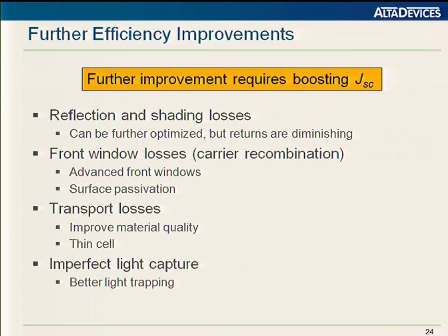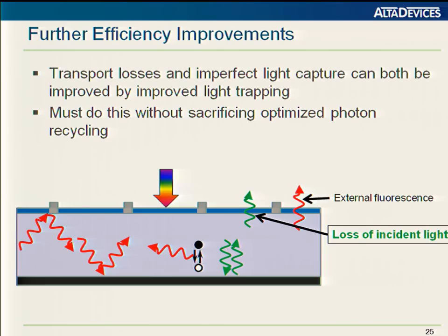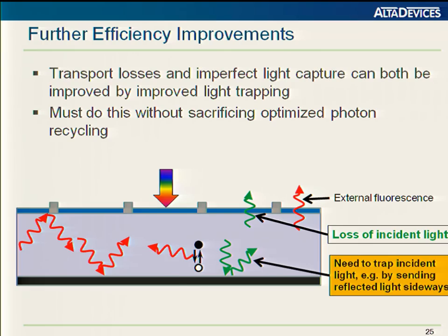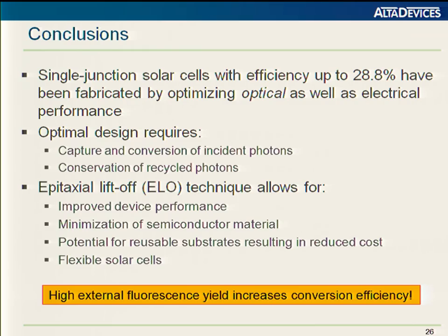We believe transport losses and imperfect light capture are really the ones to aim for in the near term. And so we're talking about transport losses in getting across the thickness of the cell and loss of light capture because of light getting out of the front of the cell. So we've already heard a lot in this conference about ways to make better reflectors, either textured or with plasmonics or diffraction gratings at the backside of the cell. I'm not going to talk in any detail about this, but I think that's a very promising area to improve the performance, even of these very high efficiency cells. Often this field tends to look at cells that are extremely thin, like 1/10 of a micron. But I think there's room for a demonstration of performance improvement even in a few micron cell. We believe JSC boosts are possible.